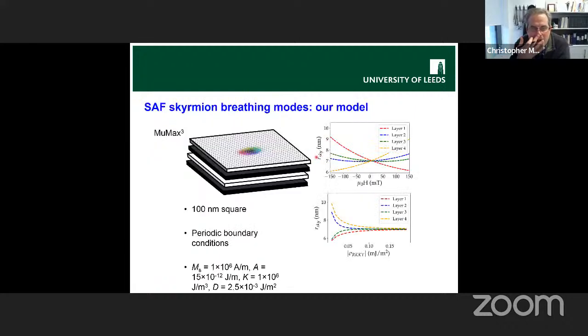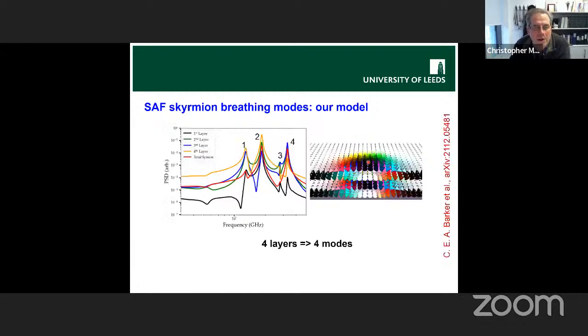So we did some simulations. You can make these things in Mumax quite easily. Here are some reasonable numbers for all the micromagnetic parameters, and you find the right sort of things. Like if you make the coupling strong, all of your Skyrmions converge to the same size, and they behave in the field the way you think. What we did was drive them with RF fields in our simulation. So here's an example. There are 4 layers, no big surprise. You get 4 modes